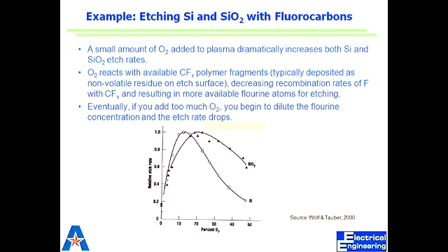But so far as silicon dioxide is concerned, whatever F has converted to HF is also contributing to etching silicon dioxide. So the etch rate for silicon dioxide does not change. F by C ratio decreases, but the etch rate does not change for silicon dioxide, while the etch rate decreases for silicon.